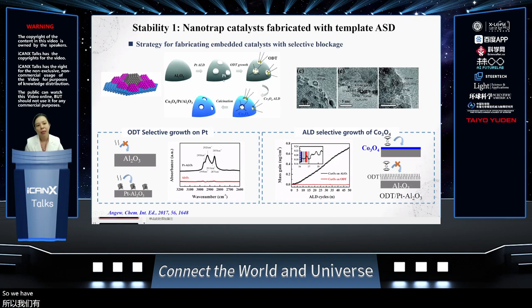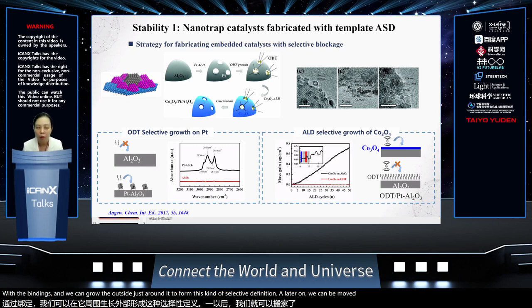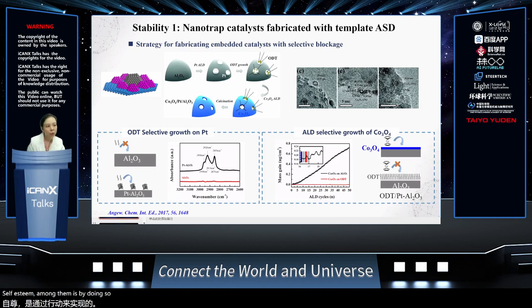We have platinum atoms, platinum nanoclusters, on this aluminum oxide support. We can apply octadecyl molecules that selectively bind to these metals only. With the binding, we can grow the oxide just around it to form this selective deposition. Later on, we can remove the self-assembled monolayers. By doing so, we're able to form the metal nanoparticles just like a basketball in the basket. If we do not run these selective processes, you would form a complete coating, and then you lose your catalytic performance.